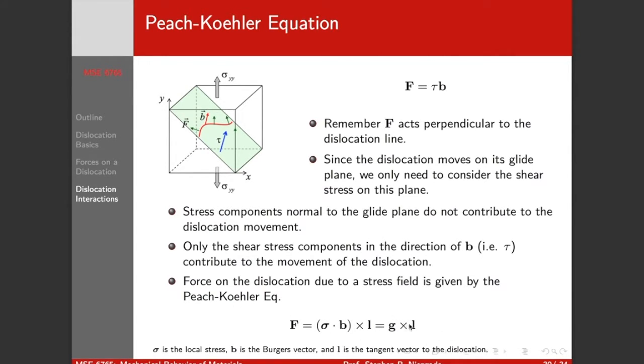So we can say the force on the dislocation due to the stress field is going to be the projection of the stress onto the Burgers vector, this gives us a vector force, a traction vector, on a plane that is orthogonal to the Burgers vector, crossed by the line length because the force is always perpendicular to the line length. That gives us the force on the dislocation, and that's the Peach-Koehler equation. Sometimes you'll see it written as G cross L, but I always like to think of it as just sigma dot B cross L.